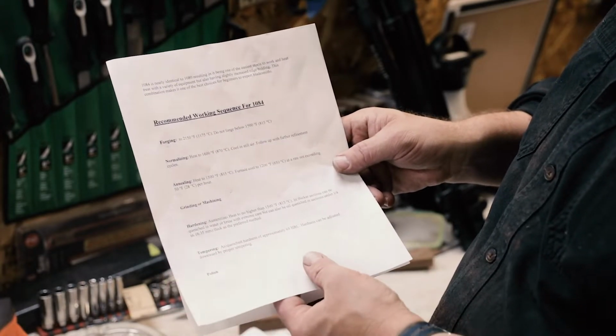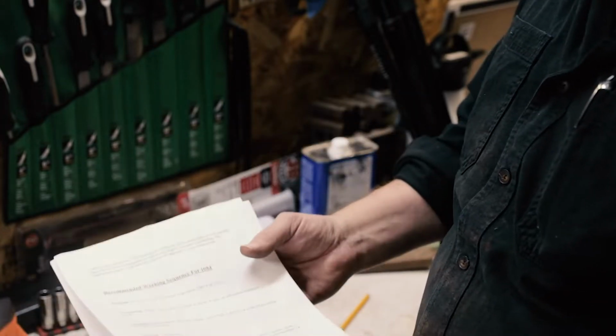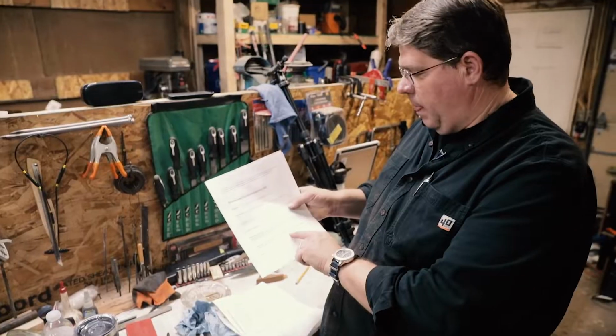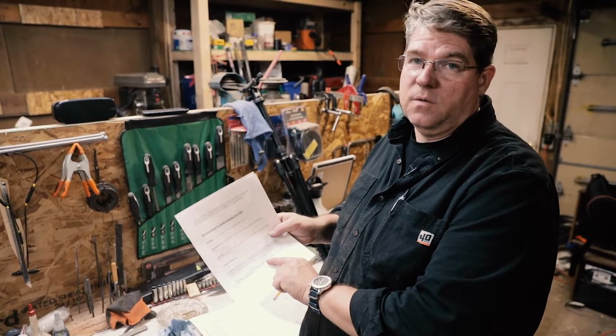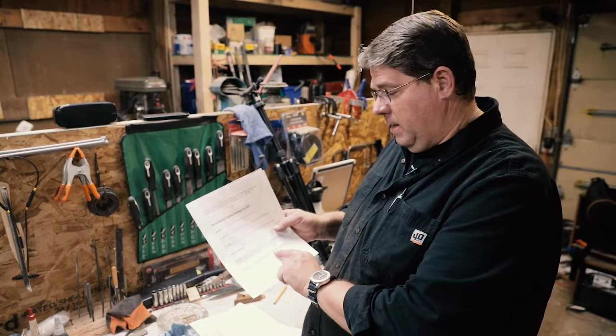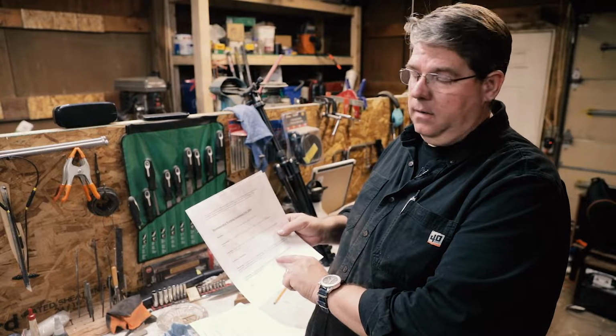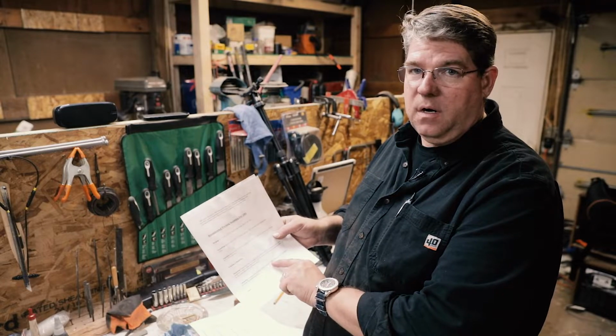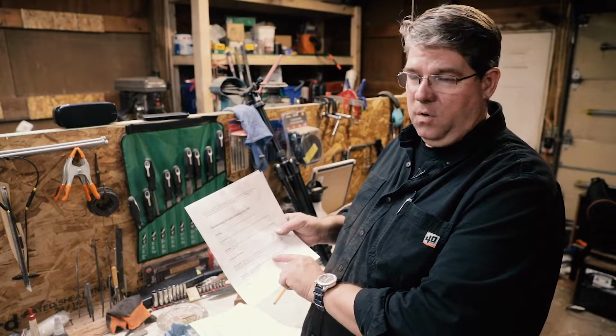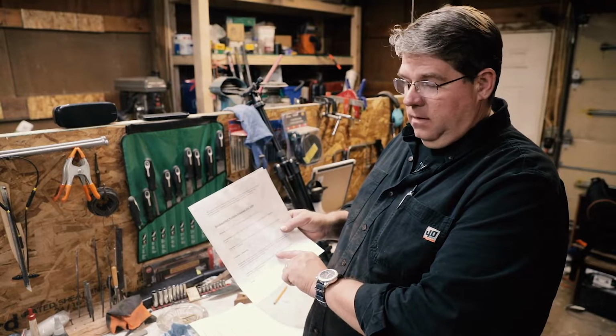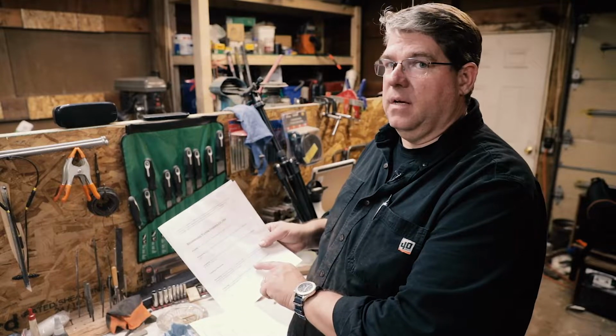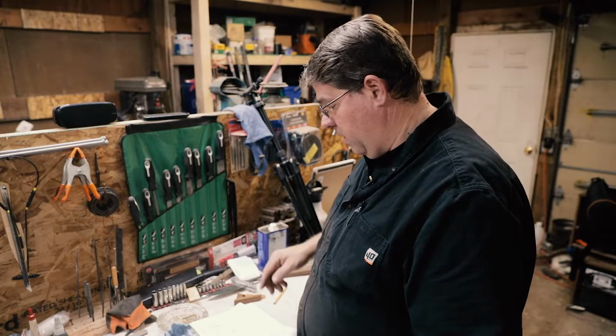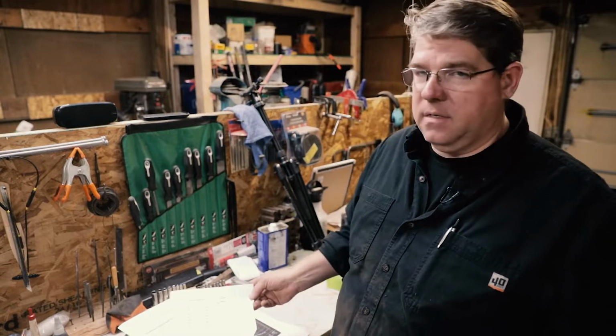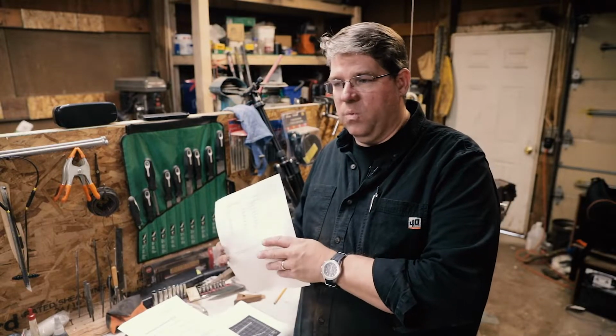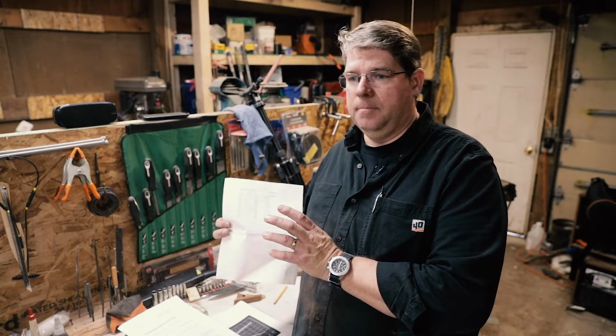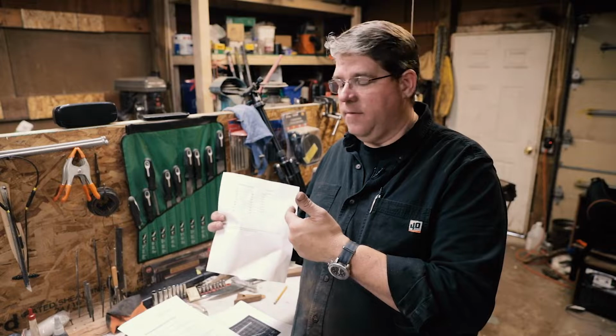Then tempering as quenched. So when it gets out of the hardening, it is approximately 65 HRC. So that's Rockwell hardness. 65 is really, really stinking hard. If you get it sharp, you'll have an edge that'll stay sharp for a long time. This is a little too hard even for chef's knives, and they don't take a whole lot of abuse. So we want to temper it, which means not necessarily make it soft, but make it more resilient and less prone to chipping or breaking in half.